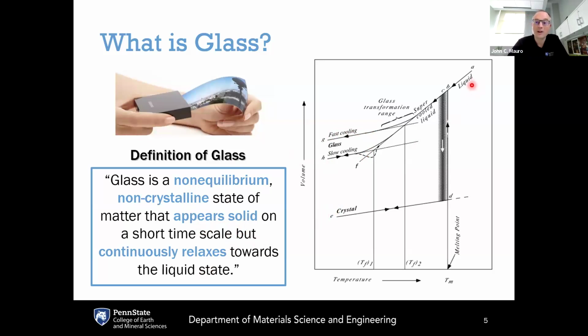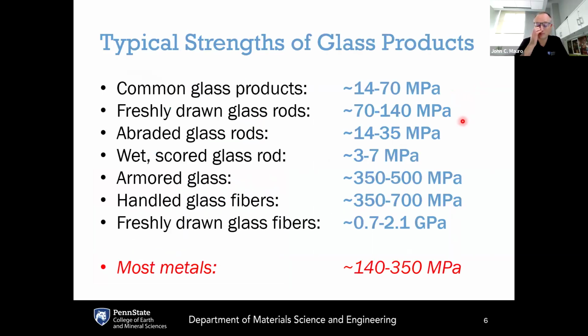And in fact, in principle, any liquid could form a glass if you cool it fast enough to avoid crystallization. So that is really the key thing. Now, when we think about typical glass products and their strengths, they range by orders of magnitude. Many common glass products, like glass jars, for example, have typical practical strengths on the order of 14 to 70 megapascals. Freshly drawn glass rods can be higher, 70 to 140 megapascals, but if they're abraded, their strength immediately goes down to about 14 to 35 megapascals.